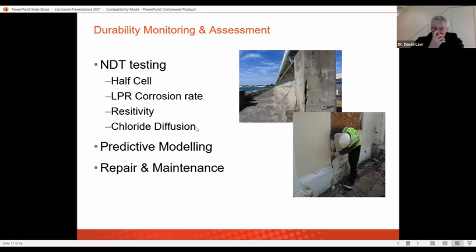And one of the things that we do when we have a mix design, we want to have a chloride diffusion coefficient for that concrete that is very low, which means that if we have a set thickness with that chloride diffusion coefficient, the chloride ions are not going to reach our steel within our design life. And to do that, we can use some predictive modeling to see whether it's going to reach our steel, and we can design to try and ensure it doesn't reach our steel. But